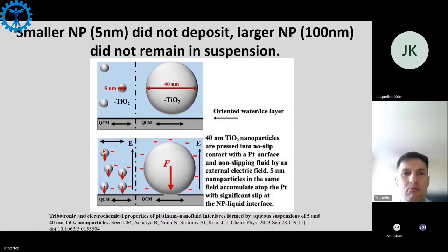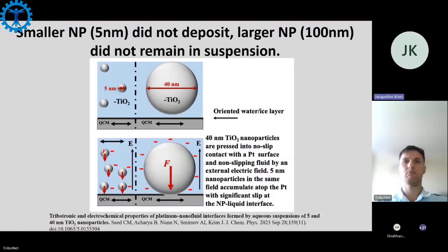Okay, this one. We checked this effect for different size nanoparticles of titanium. And the 5 nanometer sizes, no matter the range of conditions we looked at, did not show this deposition. We could press them to the surface, we could see a lubrication effect, but they never deposited. Meanwhile, for the larger ones, the 100 nanometer particles, even in the literature we see good things happening, but for our system, they did not remain in suspension.